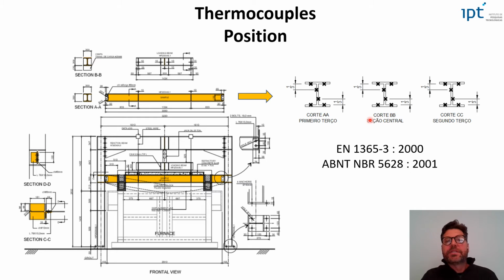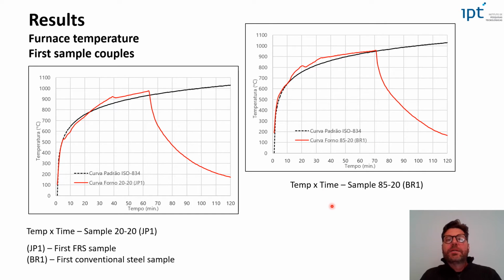This is a drawing of the system built for the tests and the position of the thermocouples over the samples. The criteria of both European and Brazilian standards for tests were met. From this slide on, I will present the results of the first pair of samples. These graphics show how close the furnace temperatures were to the ISO 834 standard curve. The left graphic represents the heating curve got from the furnace thermocouples during the JP1 test, and the right graphic represents the same for the BR1 test.